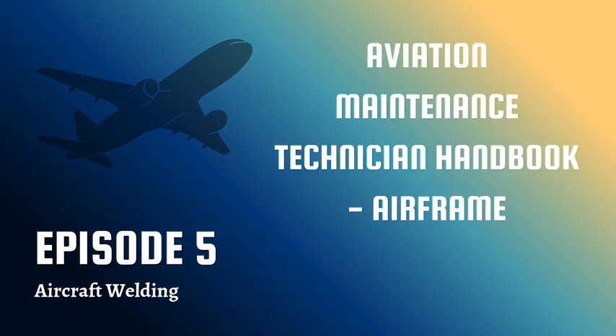If your tip is way too large, you'll deliver too much heat too quickly, risking blowing holes right through thin metal or severely overheating the base material. Oh, and a related issue. A backfire, that little pop or momentary flame extinction at the tip, often followed by reignition, is frequently just a sign that the tip orifice is partially clogged with soot and metal spatter. Cleaning the tip usually fixes it.